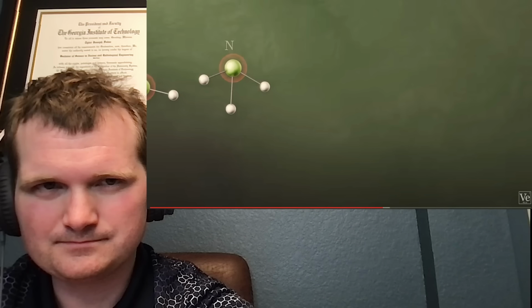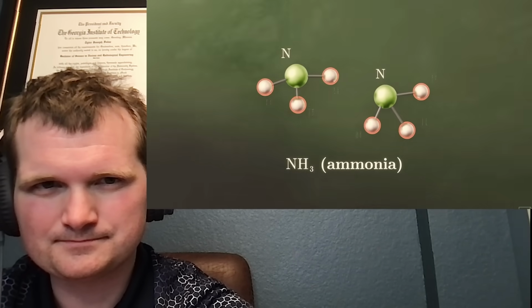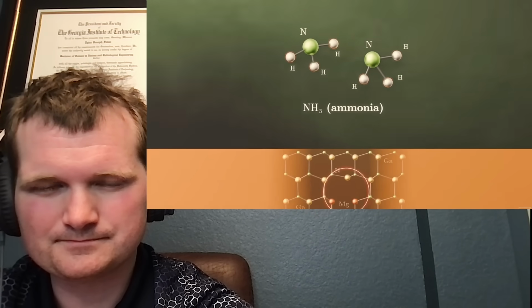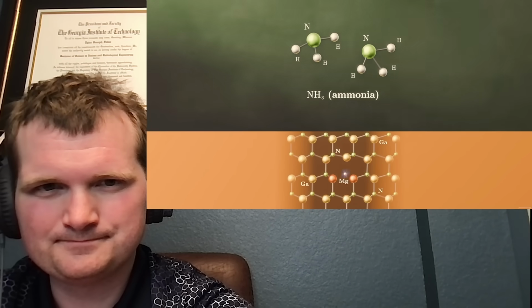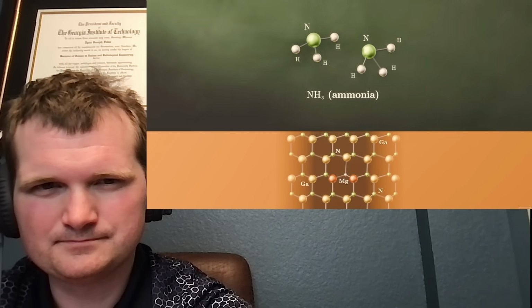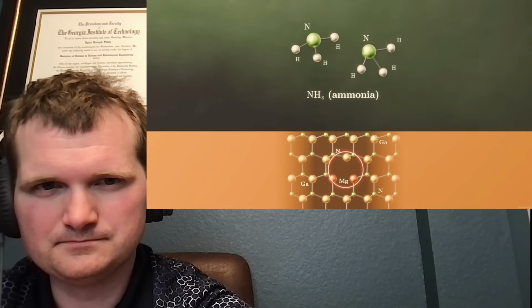His work also revealed why the P-type had been so difficult. To make gallium nitride with MOCVD, you supply the nitrogen from ammonia. But ammonia also contains hydrogen. Where there should have been holes in the magnesium-doped gallium nitride, these hydrogen atoms were sneaking in and bonding with the magnesium, plugging all the holes. Adding energy to the system released the hydrogen from the material, freeing up the holes again.